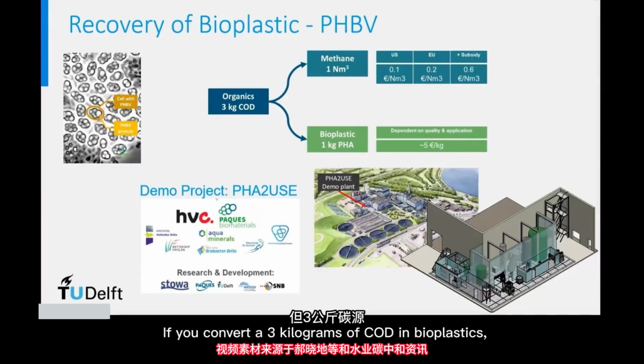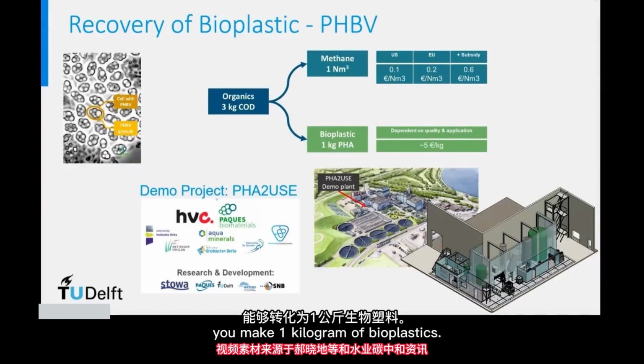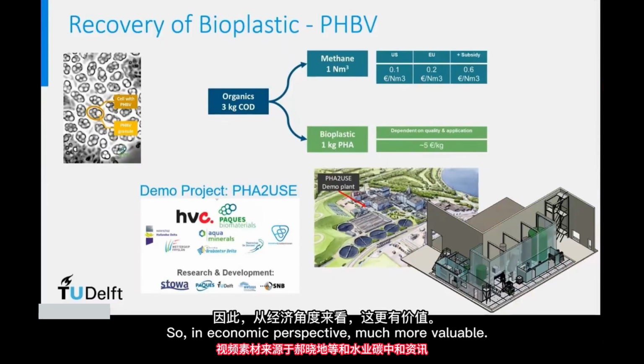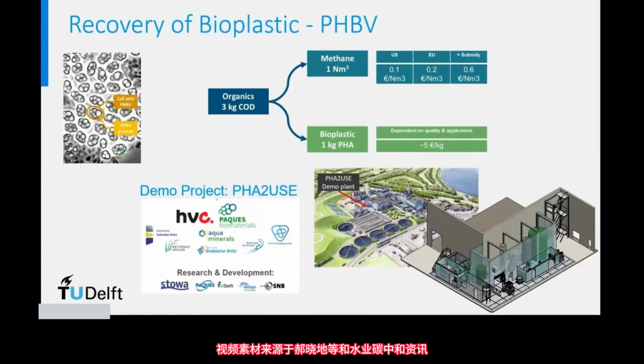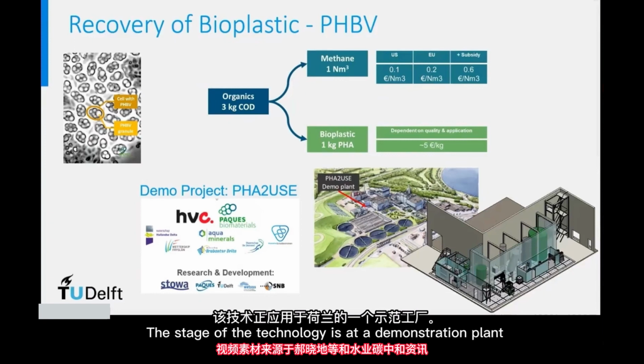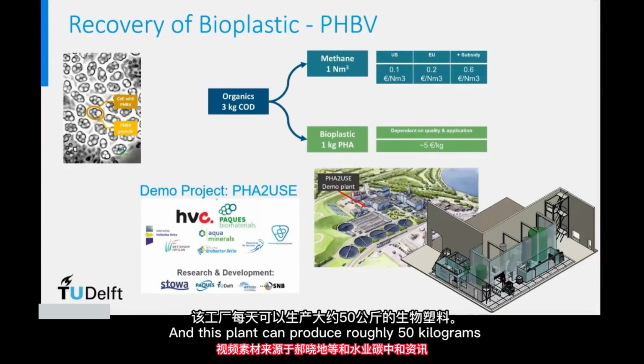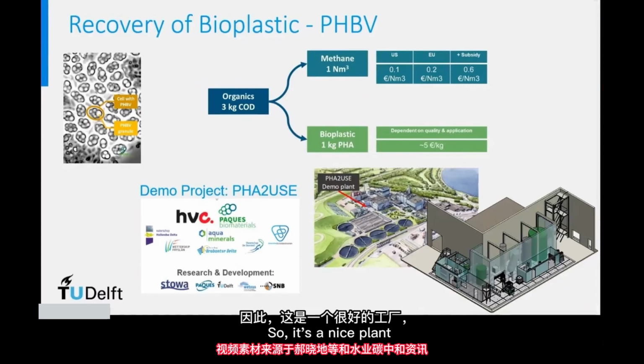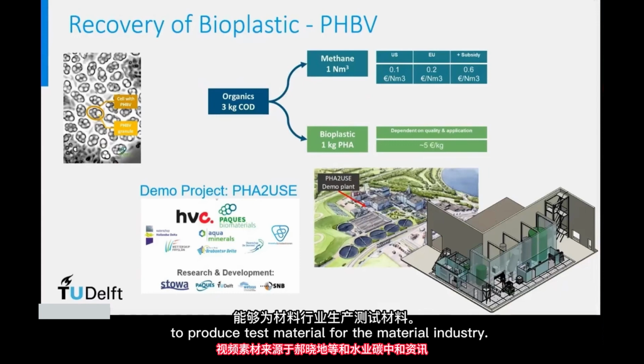If you convert that 3 kilograms of COD into bioplastics, you make 1 kilogram of bioplastics. That has a market value of roughly €5 per kilogram. So from an economic perspective, much more valuable, but we still have to develop that technology. And the stage of the technology is at a demonstration plant in the Netherlands, at the sludge handling facility. And this plant can produce roughly 50 kilograms of bioplastic per day. So it's a nice plant to produce test material for the material industry.